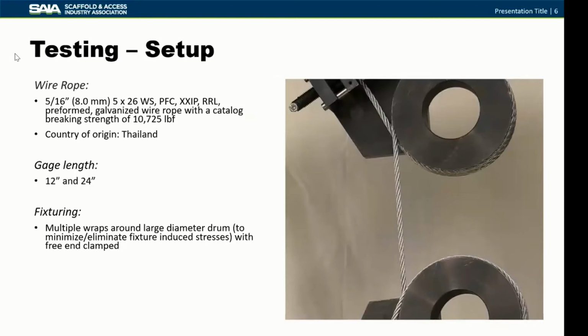The wire rope that was used is the standard wire rope that Skyclimber sells and that is used throughout the industry, basically a 5/16 or 8 millimeter. The specific rope that we used was a 5x26, a preformed extra strength rope or strands, right hand regular lay. It's galvanized and it has a breaking strength of about 10,725 pounds. The country of origin for the specific rope that was used is Thailand, and we used gauge lengths that were either 12 inches of free length of rope, or 24 inches of free length of rope. And as I said, there are multiple wraps around the drum in order to minimize any stress concentrations on the rope.